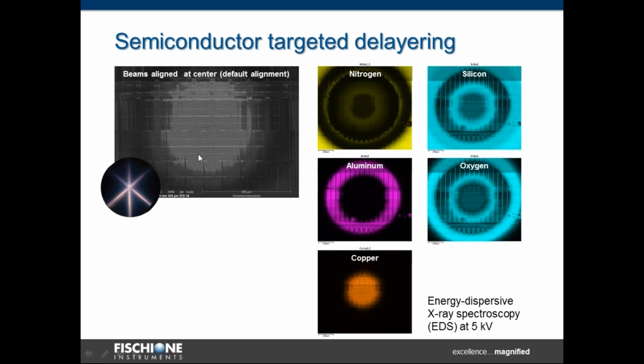We use for that purpose 3 beams crossing in the center of the stage. As you can see here, this is milled area. And why targeting delayering? Because we target one of the layer. In that example is a copper. As you can see here from EDS data, we go through this passivation layer, then first aluminum metal layer, and we stop exactly at the copper line.